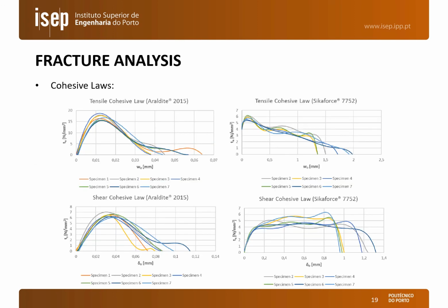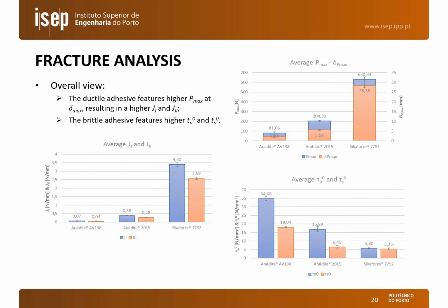We performed a similar procedure for the 2015 and 7752, and we can see that we also have a good agreement, but here we have to emphasize that the 7752 has a different shape than the other adhesives because of its ductility, so it has a higher steady state value as opposed to just a peak value, as we can see in the other two adhesives.